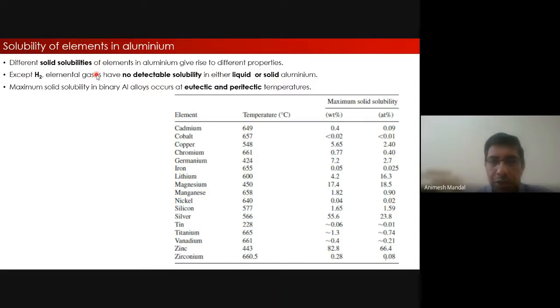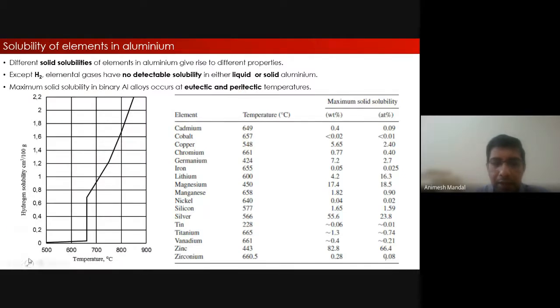The other important thing which is to be noted when we deal with aluminum is the hydrogen. Hydrogen is, I will say, undesirable in your aluminum alloy. So we need to keep the hydrogen to a minimum. If you see the diagram, even in solid aluminum, this is the pure aluminum melting point. The melting point of pure aluminum is roughly 660 degrees centigrade. So towards the left, what we are seeing is, even in the solid state, hydrogen is diffusing into aluminum. And as it melts, you can see there is an immediate pickup of hydrogen, and in the liquid there is an exponential rise in solubility of hydrogen. So that is what this particular plot tells you. It tells you about the hydrogen solubility in pure aluminum as a function of temperature.